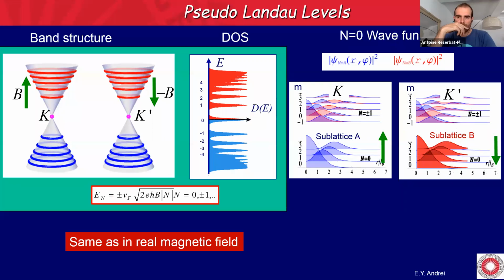Now, what's important to realize, whether you have a real or a pseudomagnetic field, is that the wave function in the zeroth Landau level is valley polarized. So the wave function in the K valley is all sitting on the A sublattice, and the wave function in the K prime valley all sits on the B sublattice. So it is valley polarized. Now, when you have an external magnetic field, this is totally irrelevant because we can't tell the difference. However, with a pseudomagnetic field, if you're able to separate the field up and field down, as I showed that you can do, you can actually see this valley polarization.